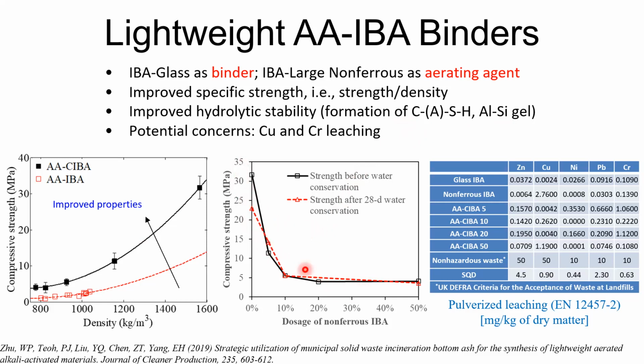After the addition and mix of the non-ferrous particles and the glass, the hydrostability was actually improved. So with the increment of the non-ferrous IBA, on one hand this IBA was serving as the aerating agent, but on the other hand it also provided sources to form CaSH and aluminum silica gel.